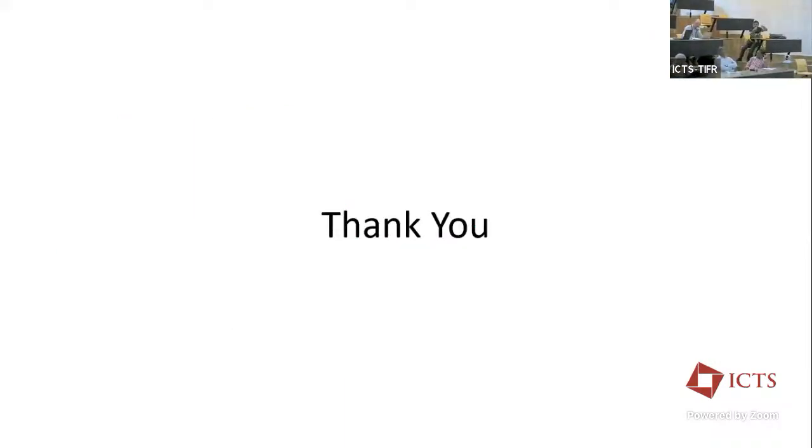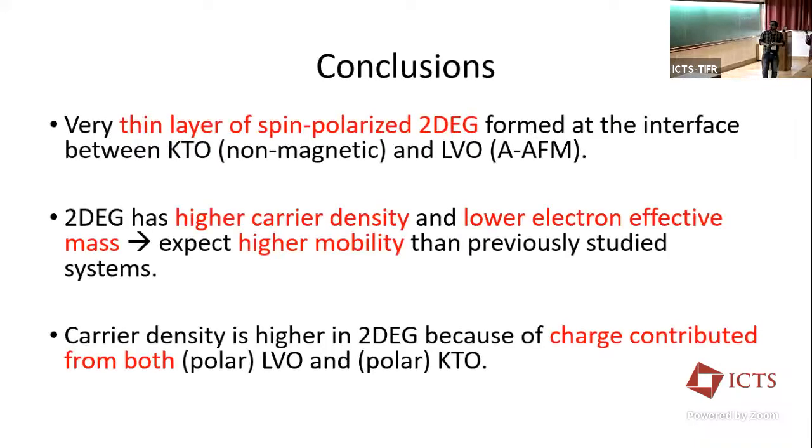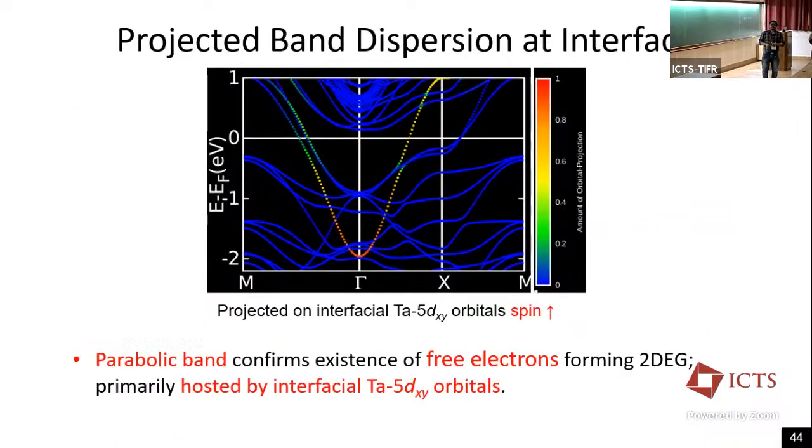And in the 2D, is it isotropic? Isotropic means? So you are talking about an effective mass of 0.11, I believe, right? Okay, so you are asking whether this is the same in all directions or not? Yeah. Okay, actually we found there is very little difference, 0.11 or 0.14, something like that. So along gamma-X it is 0.11, and along gamma-M it is 0.14.